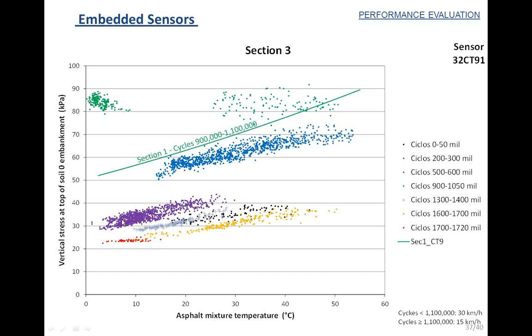In cycle 200,000, you have these points. For 500,000 cycles, we have the blue point, and after 1 million cycles, we could see this high level of damage. And this was even surprising for us, because the level of damage here, we knew that level of damage was very high because we saw the performance of the section. We knew the section were highly cracked, but we were surprised to see a level which was over the stress that we measured in a fully flexible pavement.